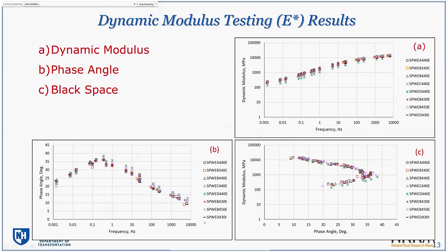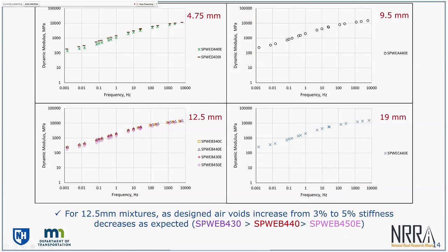But the next slide allows us to look a little bit closer at what happens to these mixes as we change certain things. If we just focus on the bottom left here, we are looking at stiffness at different frequencies for all half-inch mixes. The main difference between them is the design air void level. And we more or less see what we expect. As we go from 3% to 5% air void levels, in general, the stiffness of these mixes is decreasing. So nothing surprising, as expected. It's always good to see that confirmation.